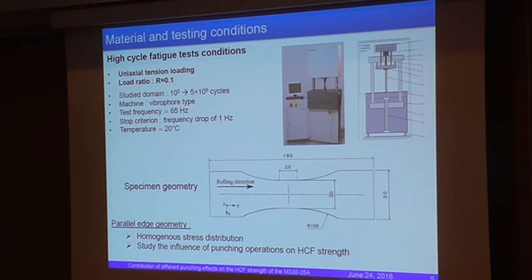I didn't mention that the ultimate goal is to design electrical machines for stop and start. So we are designing for tension conditions. So we used a 0.1 load ratio, but as you can imagine, it's difficult to use negative load ratio with such thin sheets. So here is the specimen geometry. In order to study the influence of the defects on the edges, we used parallel edges. So we have 2 20 millimeters long edges with homogeneous stress distribution.